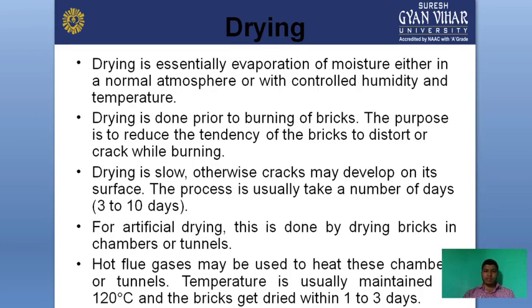Drying is essentially an operation of removing moisture either in a normal atmosphere or with controlled humidity and temperature. Drying is done prior to burning of bricks. The purpose is to reduce the tendency of bricks to distort or crack while burning. Drying should be slow, otherwise cracks may develop on the surface. The process usually takes 3 to 10 days. For artificial drying, bricks are dried in a chamber or tunnel at about 120 degrees and get dried in 1 to 3 days.